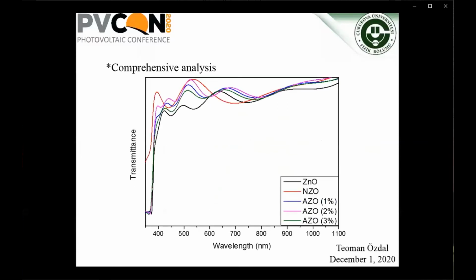However, optical properties were obtained close to each other, except for the N-doped sample. The optical transmittance of the N-doped sample in the UV region is less than the others. All the films gave an interference pattern.